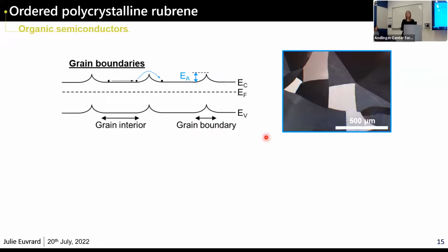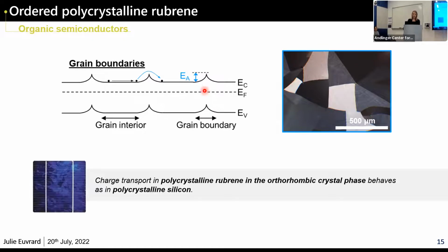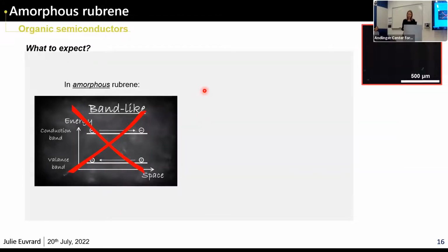What we think is happening is what is happening in polycrystalline silicon, actually. You have band-like transport inside the grain, but then when the charges have to travel, they have to cross certain grain boundaries. And those grain boundaries are not energetically favorable. So you have to provide energy to the charges to be able to jump over this barrier. So in the end, what we see is that transport in polycrystalline rubrene behaves in a very similar way as transport in polycrystalline silicon. What about the other extreme case, amorphous?